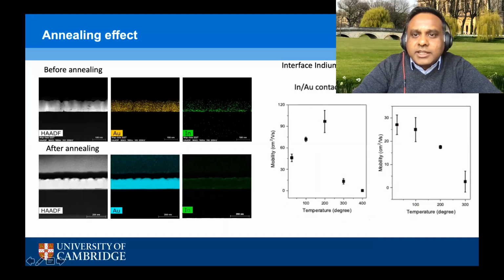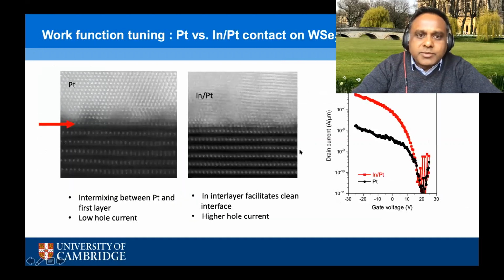Now, this annealing is really tuning and refining the interface, because if we plot the mobility as a function of annealing temperature for the indium gold contacts, we see that there is some increase up to 200 degrees C, after which we start to get a decrease in mobility. And when one compares to pure gold contacts, there is a decrease in mobility almost right away with annealing temperature. We feel that the gold starts to react with the 2D semiconductor and disrupts the interface right away. In the case of indium, the indium provides a buffer, preventing that reaction from happening.